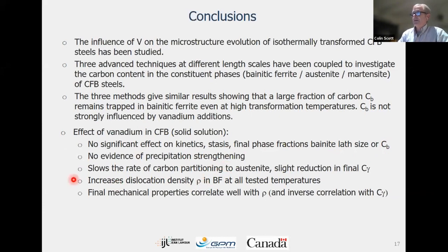It's not that. It's not precipitation strengthening either. We do see a change in the rate of carbon partitioning to austenite and maybe a slight reduction in the final austenite carbon content. But the main thing is this dislocation density is changed. It's increased at all tested temperatures. And the reason for that increase is not completely clear yet. It's complicated. But we do see quite clearly that the final mechanical properties correlate very well with the dislocation density, and there is an inverse correlation with the retained austenite carbon content. So thank you very much for listening.